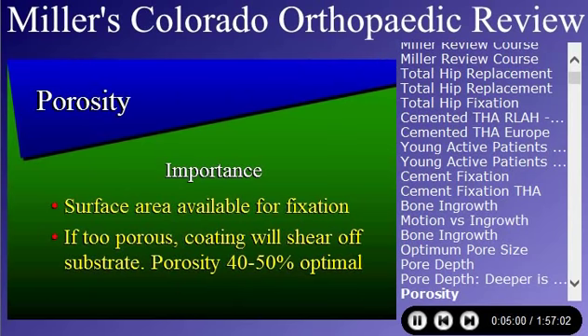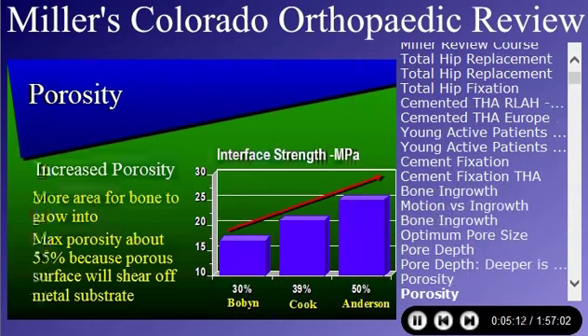So if it's too porous, however, the porous coating will literally shear off the metal and fall off. So yeah, the optimum porosity is around 40 to 50%. So here's a study showing if you increase the porosity from 30% up to 40 to 50%, you have increased shear strength and pull-out. And the maximum porosity is about 55% because after that, the porous surface becomes so weak that it literally will shear off.